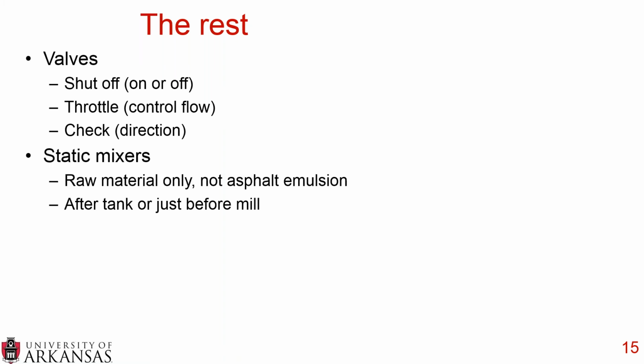You can also have static mixers you only use on raw materials. So you only use it on the asphalt binder, the soap solution, the chemicals, the emulsifiers. You do not use a static mixer on asphalt emulsion. That'd be a great way to damage your asphalt emulsion. And you either have a static mixer just after that raw material tank or just before the mill. Kind of depends on the type of setup you have. And I'm going to get to that in a second as well.